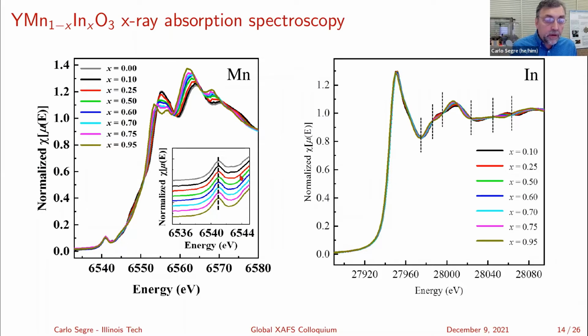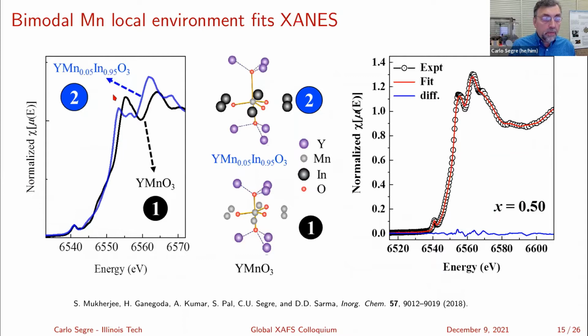The isosbestic points that you see here in the manganese and in the indium, although they're not quite as developed there, not quite as obvious, but both the manganese and indium show isosbestic points. And that sort of tells us that we're looking at something that's not necessarily randomly mixed. So we decided to take a different approach to the fitting. And we decided to fit the endpoints for the manganese and the indium. And so this is the manganese 0.05, indium 0.95, and this is the pure manganese. And you can see there are significant differences. And if we fit these individually, we get different local environments. And I'll detail that a little bit more later. But in the future, I'll be having the blue being the dilute manganese and the black being the pure manganese, sort of following the colors.